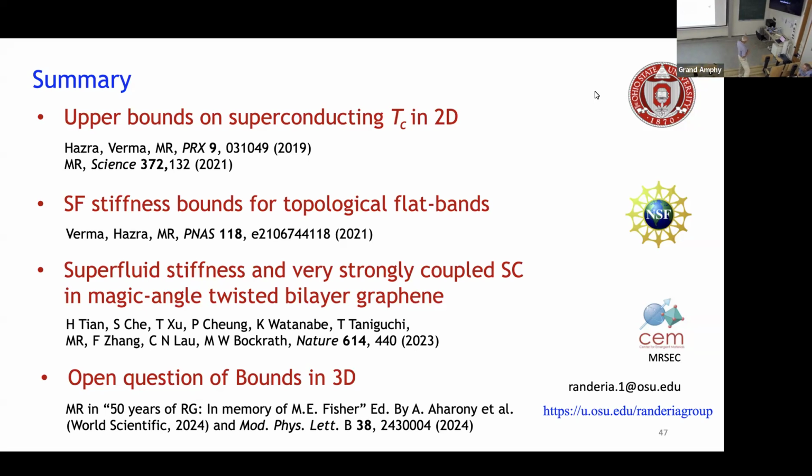In superfluid helium, you can do the Andronikashvili torsional oscillator experiments to measure the superfluid. In superconductors, you can do either two-coil measurements, kinetic inductance, or other measurements to measure the superfluid. That's a response function which shows a singularity. In the hydrogen molecule case, there's no response function that shows any singularity as you change parameters, ever.